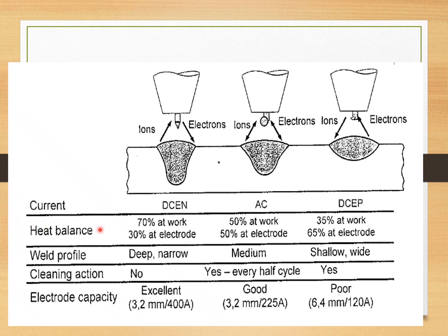So heat balance. DCEN: 70% at work and 30% at electrode. For alternating current, 50% at work and 50% at electrode. For DCEP, 35% at work and 65% at electrode. For weld profile, DCEN is deep and narrow. For alternating current is medium. Direct current electrode positive, shallow and wide.